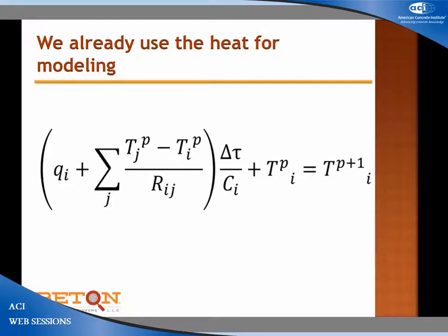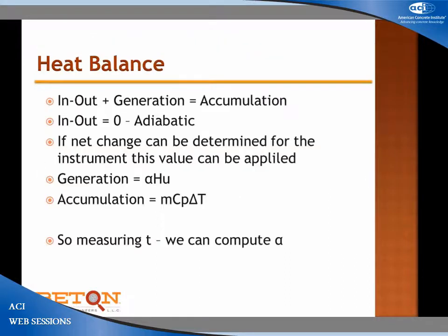But we can write a heat balance, because that's all that was. And we can say that in minus out plus generation equals accumulation. It works for your bank account. It works for a concrete member under adiabatic control, because you remember under adiabatic control, in minus out is zero by definition. And if you can determine the net change for the instrument,